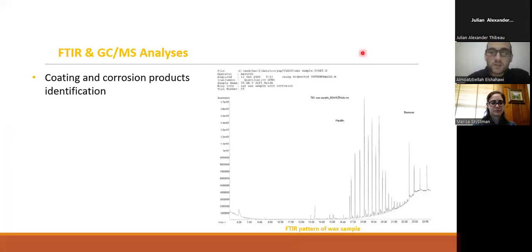Materials suspected to contain wax and corrosion products were supplied for characterization. They were analyzed by Fourier transform infrared spectroscopy, FTIR, and gas chromatography mass spectrometry, GCMS. FTIR results showed that the corrosion product best matched copper chloride hydroxide, and the 19th century coating was analyzed and found to be a mixture of beeswax, paraffin wax, and an oil, as we can see here from the FTIR chart.